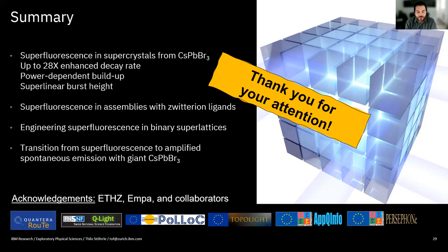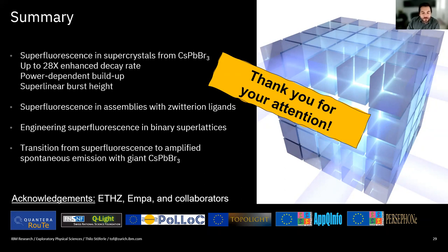A question from the host regarding exciton binding energy: since this audience works on polaritonics and wants to place perovskites into microcavities, what are the exciton binding energies of the materials in supercrystal form? Typically they have at least several tens of meV — typically more than 100 meV. In the quantum dot environment, the exciton cannot delocalize much because it is also confined by the quantum dot itself. The exciton binding energy is large enough to survive at room temperature.